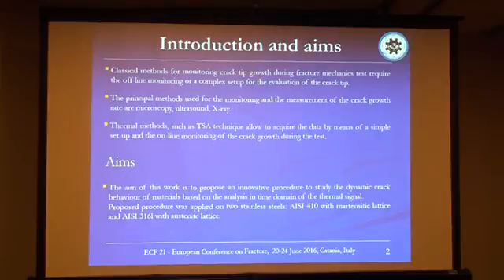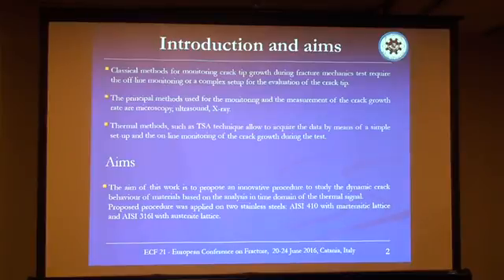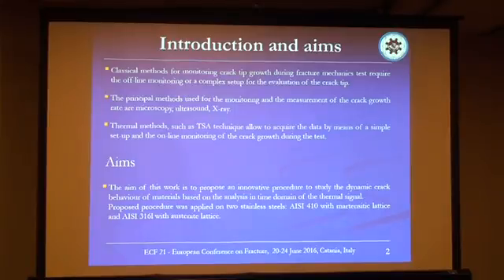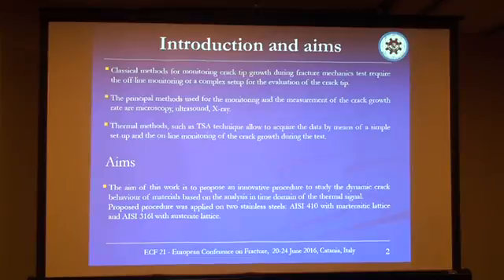Classical methods for monitoring the crack tip growth during fracture mechanics tests require offline monitoring, or also online monitoring, but with a complex setup for the evaluation of the crack tip position. The principal methods used for monitoring are microscopy, ultrasound, and other methods. With thermo-methods such as thermo-elastic stress analysis, we can also evaluate the crack position and the stress intensity factor within the same dynamic test using an infrared camera.